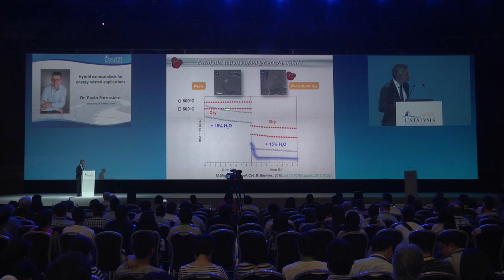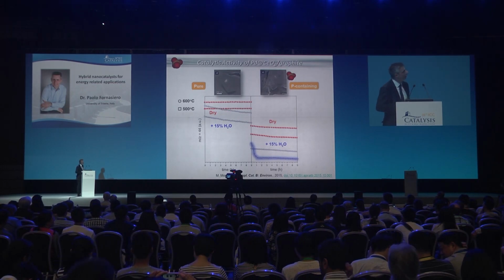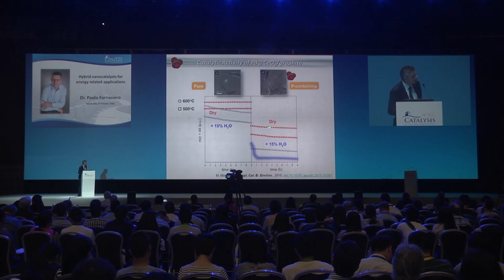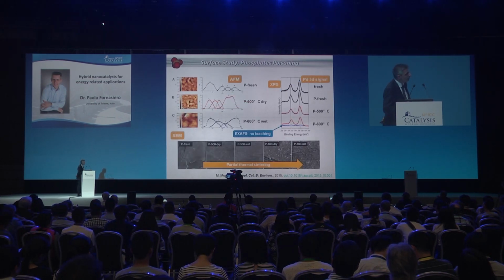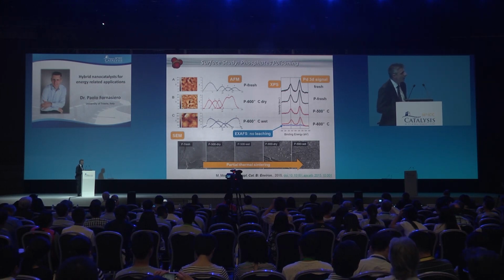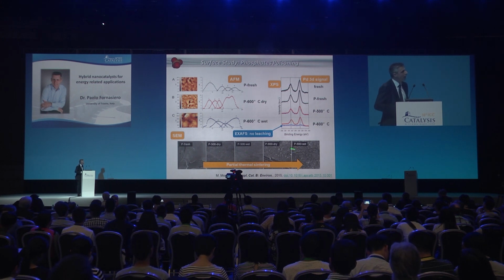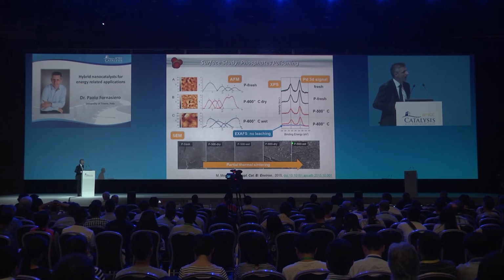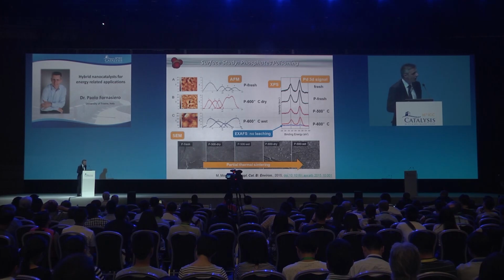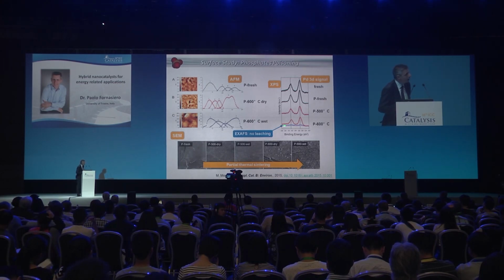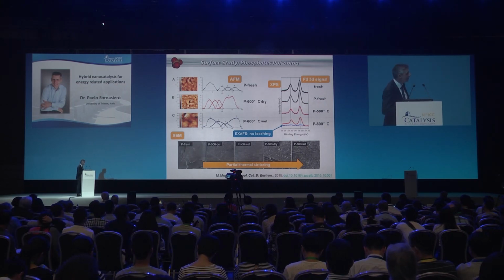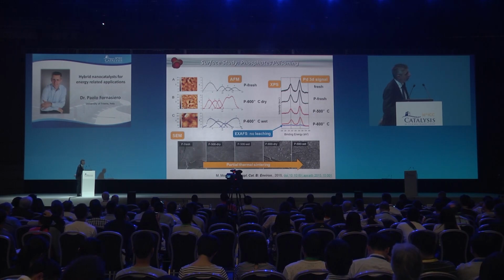The operando techniques tell us that under dry conditions the catalyst is stable in the absence of phosphate, and there is deactivation, as we already observed, in the presence of water. However, if you have phosphates, even under dry conditions, the catalyst starts to be deactivated. And with the co-presence of water and phosphate, the catalyst is completely killed. We did lots of investigation to understand this phenomenon, and all the techniques tell us that in the presence of water, high temperature, and phosphate, you form stable cerium-3 phosphates, which really cover the surface. You no longer see the signal of palladium, which is buried inside the catalyst, and ceria is not flipping between cerium-3 and cerium-4 plus, so there is no catalysis involved in this system.